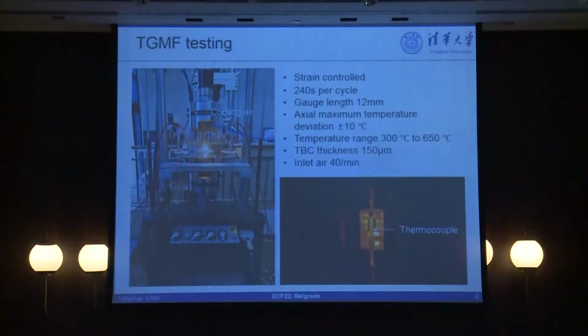And now we come to our test facility. We established a special test facility. It's a conventional machine here. This furnace is heated by radiation. We use lamps focused on the specimen. We can heat up the specimen very quickly, within seconds. We do not measure the maximum temperature. Anyway, we can bring material to melt immediately, in seconds.